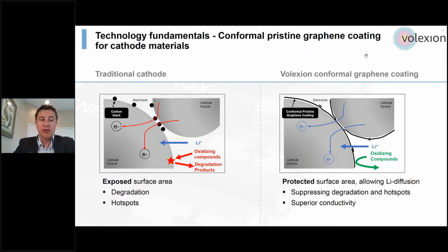On the left-hand side of my page, what you see is the traditional approach of assembling lithium-ion battery cathodes, where the active particle, the large gray spheres on this schematic, are mixed together with little teeny beads of carbon black, which are the small black spheres, and this mix swims in the liquid, which is the electrolyte, which ensures the ionic conductivity between both sides of the battery. And this traditional design, which is the one that you encounter in cell phones, specialty applications, and EV batteries, leaves very large surface of the cathode particle exposed to the electrolyte, which is an oxidizing environment, particularly at high charge rates. So the electrolyte compounds can have access to the surface, degrade themselves, and degrade the material at the same time. So that leads to accelerated aging and also to the formation potentially of hotspots due to the point-to-point contact nature of the carbon black.